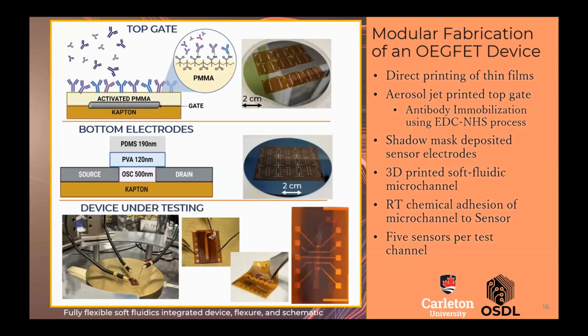So we can build on one substrate up to 25 to 50 devices. Every one of these has 5 biosensors on them. Currently, shadow mask PVD deposition, so low temperature physical vapor deposition, is what we're using for the source drain electrodes. For the top gate, we have now switched to aerosol jet, which makes life a lot easier because then you can do all of that at room temperature. And this is where most of our functionalization is, on the top gate. And then we assemble it using a chemical adhesion process.